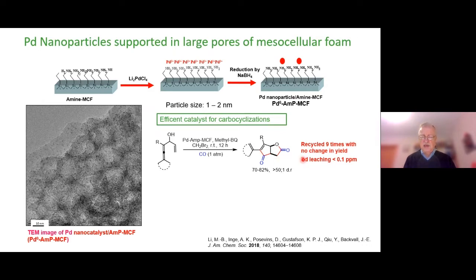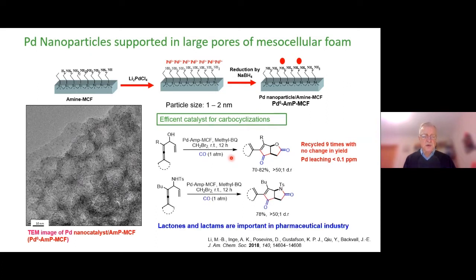This reaction can be recycled 9 times without any change in yield. The palladium leaching is actually less than 0.1 ppm, which is excellent because you cannot detect any leaching of palladium. And you can also use this reaction for the corresponding amines, as shown here, and then you get lactams. And lactams are important in the pharmaceutical industry.